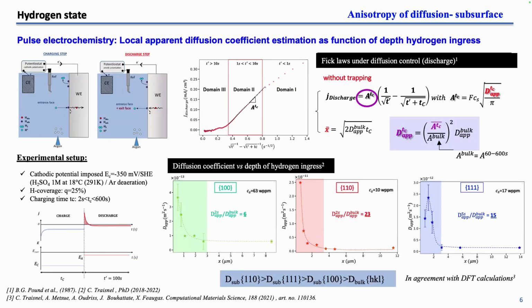The second interesting point is that we can also check the surface behavior. We perform a pulse electrochemical technique: we charge the surface, stop the charging condition, and then follow the flux during the desorption. With this curve, we can model it with Fick's law and extract the apparent diffusivity.